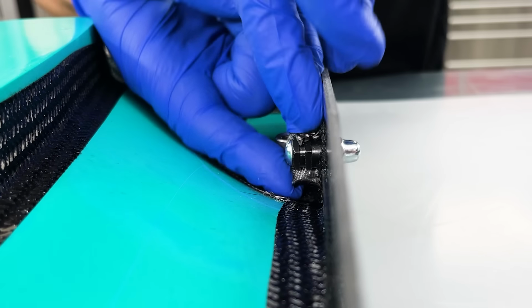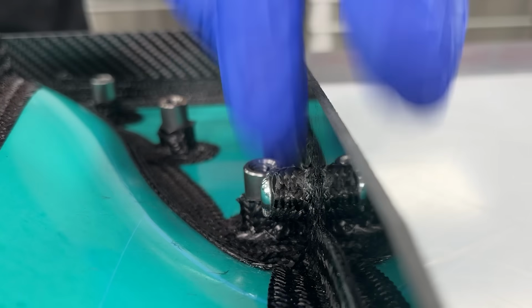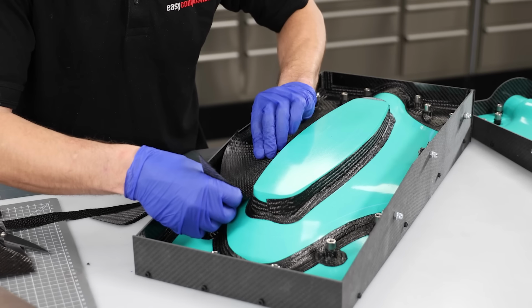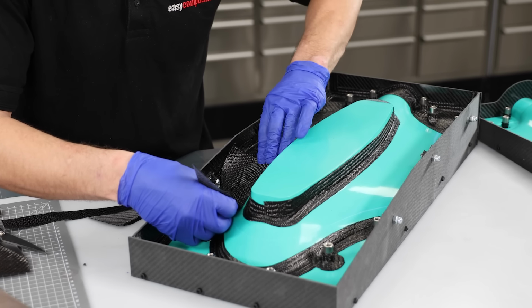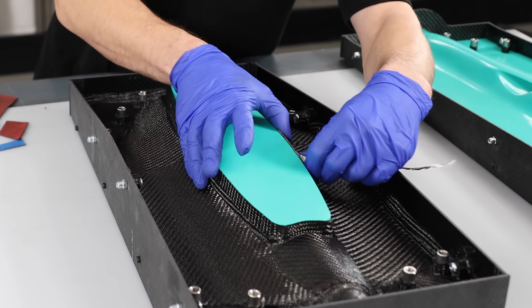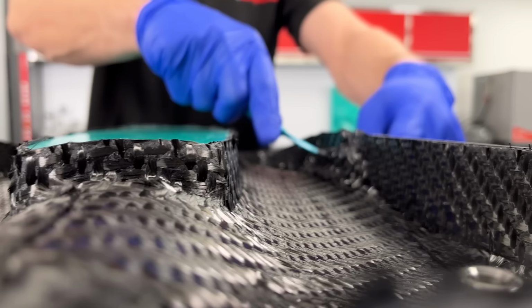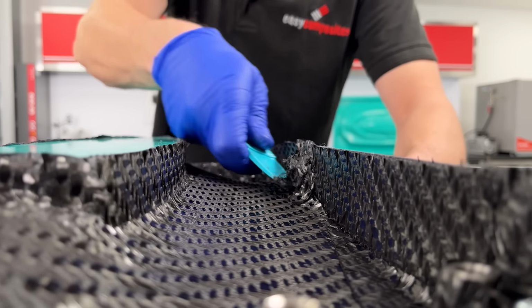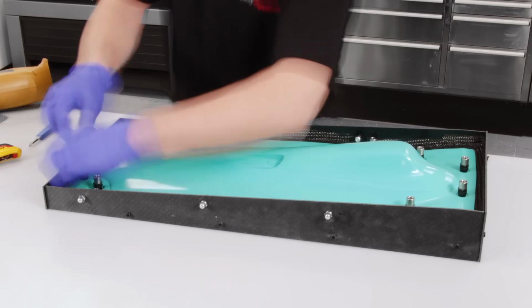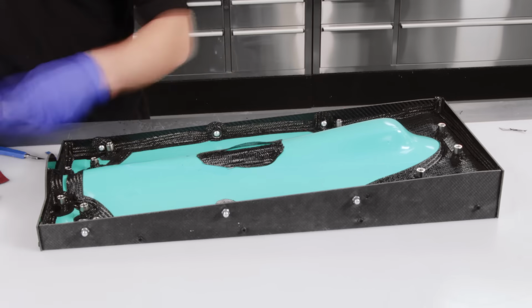The sides of the bushes are then wrapped with a ply of the 45-degree strip before the rest of the mould is laminated as normal. As with any tooling layup, this can be done in multiple pieces to make the lamination easier. We then repeat the exact same process with the second pattern.